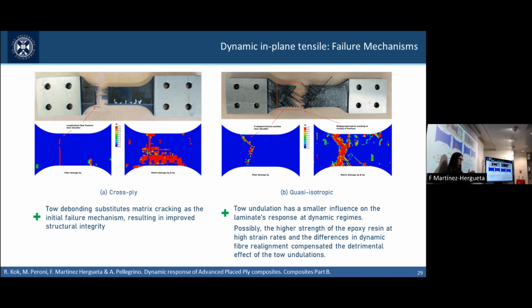So the strain gradients increase in time as the toe realigns. When we do this on a dynamic basis, we don't give time for that toe to realign. That means that the strain gradients that we were generating before don't have such a high magnitude. So those mechanisms tend to compensate, such that at this dynamic regime there is not such a high difference in tensile response on the cross-ply laminate in particular. So this is a little bit of the future work to be done. Further investigation on the dynamic fiber realignment will really shed further light on this. But nevertheless, it gives a good opportunity to further investigate these materials for aerospace applications.